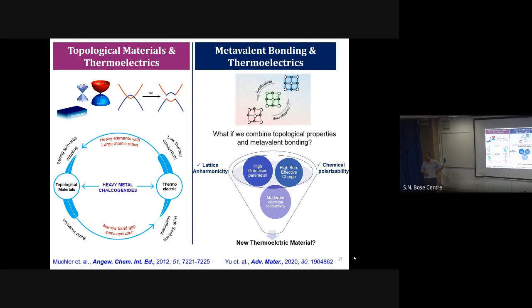So local ferroelectricity can come from many reasons. That I have not told here. Because if you look at this compound very carefully, I didn't talk about lone pair. I'll talk about that right now, because it has a bismuth 6s2 lone pair. So what I believe in this compound is that locally the octahedra are distorted because of the bismuth lone pair expression, which is called the inert pair effect, which is breaking here. We have synchrotron PDF data, which shows the local structure is different from the global structure. So globally the structure is not ferroelectric, but locally it has a ferroelectric instability, which generates lots of low energy optical phonons. But of course, for thermoelectrics, global ferroelectricity is not needed.